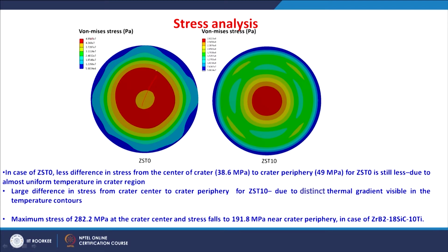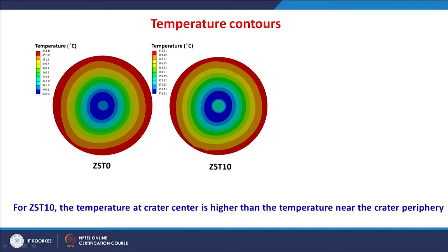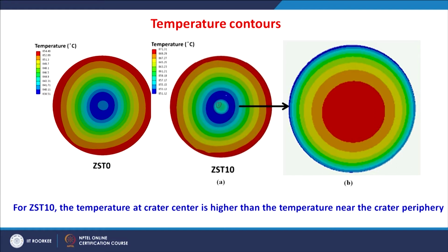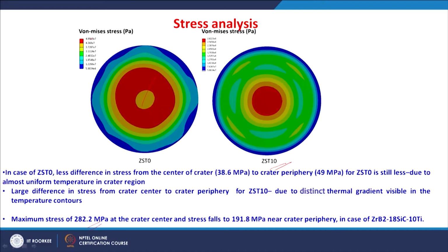But if you see the ZS T10, there is a large difference in stress from the crater center to the crater periphery. This is mainly because of the distinct thermal gradient visible in the temperature contours. So, you can see there is a large difference in the temperature contours, and you can see the center of the crater is hotter. So, for ZS T10 the temperature at the crater center is higher than the temperature near the crater periphery. So, the stresses found were also very large in case of ZS T10.